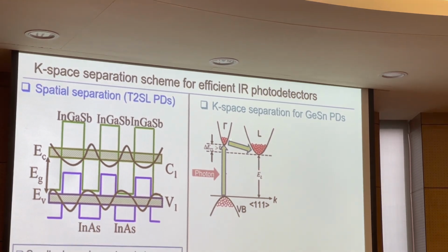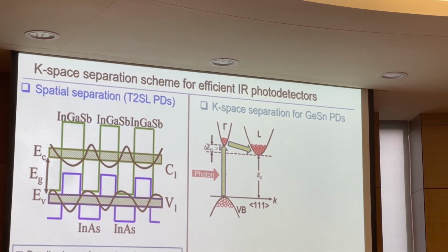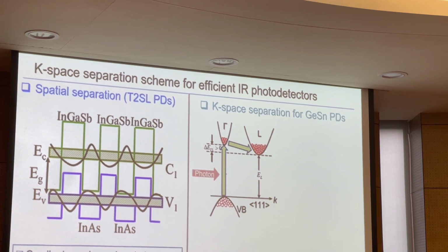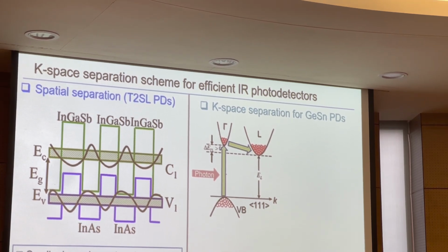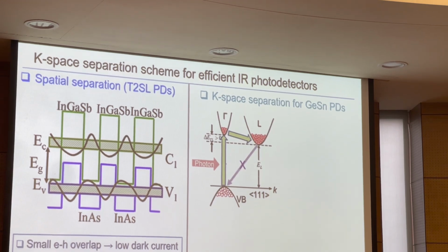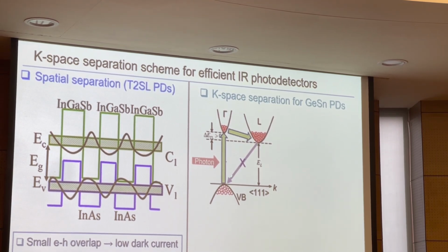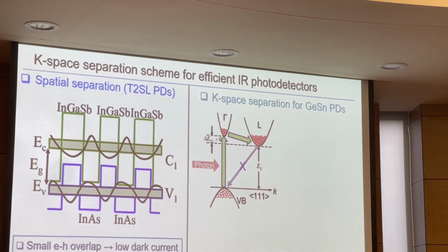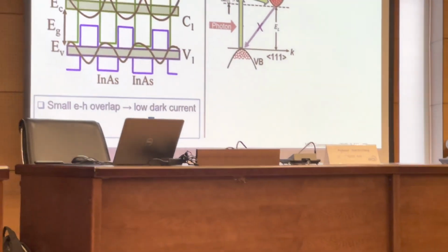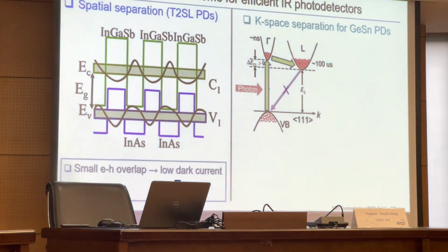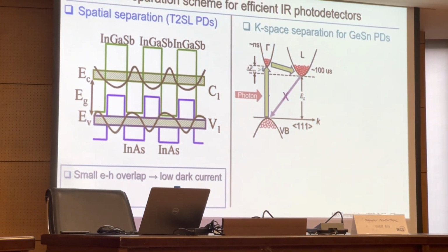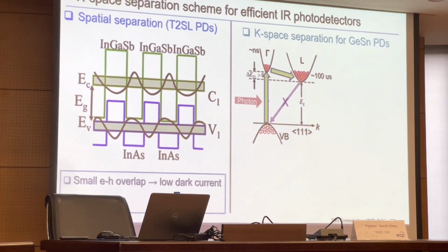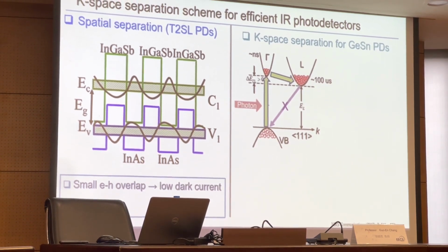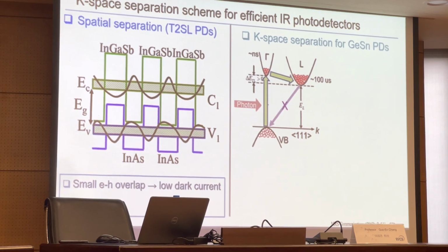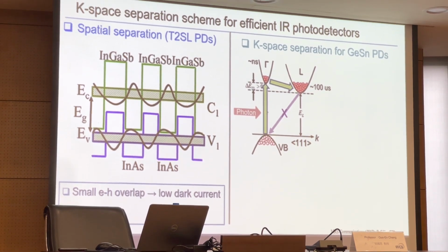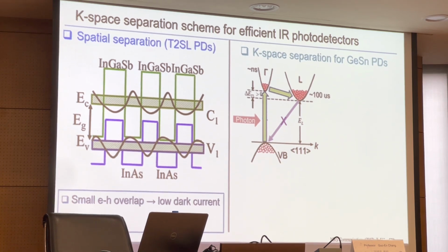So those electrons will quickly relax to the L conduction band because the energy state is lower. Due to momentum conservation, this indirect bandgap recombination rate is very small, which means the lifetime is very long. For electrons in the direct conduction band, the lifetime is like a nanosecond, but for electrons in the L conduction band, the lifetime is about 100 microseconds.